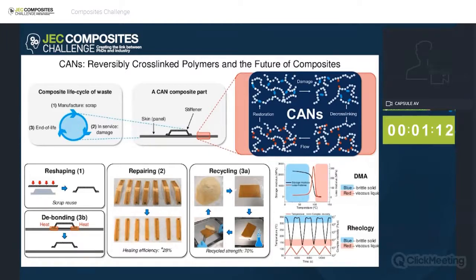And in the photos, we can see at the bottom of the slide here some 3-point bend specimens where I've demonstrated this. So we can get really quite good healing efficiencies with composite and polymer made of these CANs, but I've deliberately left in this low one here with this 28% healing efficiency as a little reminder what we cannot do is repair fiber damage. So that's why that is quite low there.